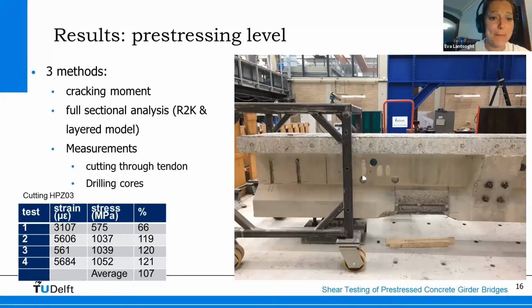And then we also tried to measure this by first drilling cores and seeing what would be the strain release in the concrete. And we did that by measuring with an LVDT as well as with the digital image correlation. And we also did the destructive method of cutting through the tendon and just measuring the difference in strain as the tendon is released.